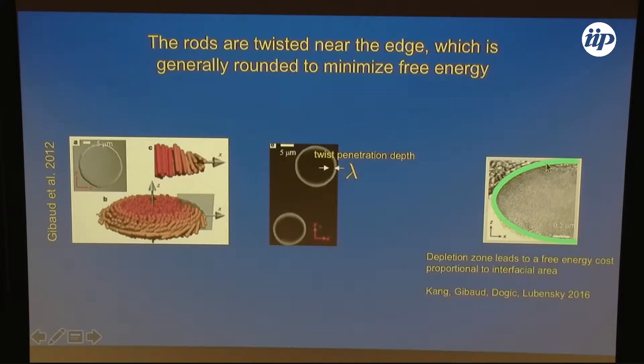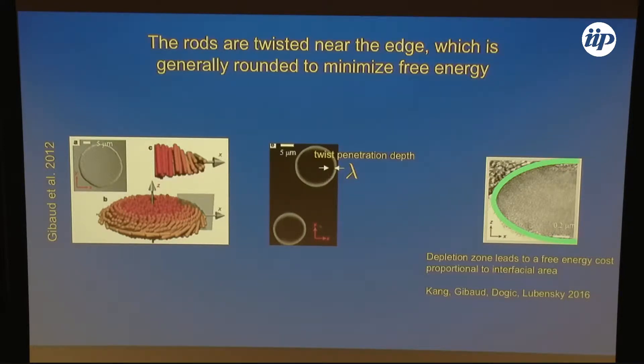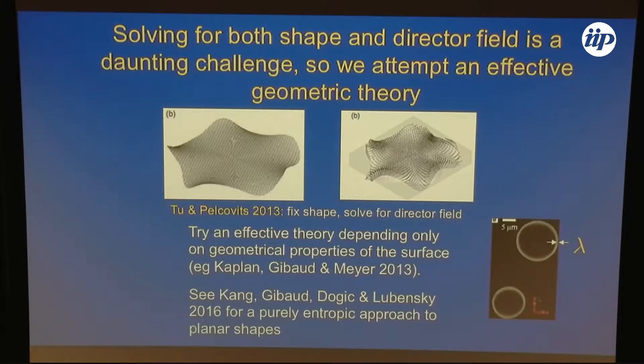Remember these polymers — you can think of them as little hard spheres, and the centers of those spheres can't get any closer to the interface. This is a side view, an electron micrograph of the edge of a membrane, and the green layer is the layer from which the centers of these polymers are excluded. There's a free energy proportional to the interface between the rods and the solution. Just like an ordinary droplet, that interfacial energy doesn't want to have sharp edges — it wants smooth edges, and it can do that by twisting the rods. So we're going to try to explain these three-dimensional shapes by putting all the liquid crystalline properties into properties of the edge, like a line tension and other effective properties.